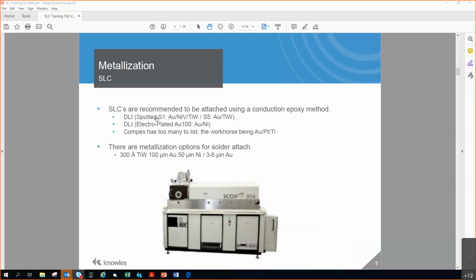What it didn't do is mesh well with our manufacturing process for DLI, because we do a lithography process, which doesn't go well with platinum. Compex uses what they call a scoring process, and basically it's a skim dice. They dice their borders around their parts, and that's fine. With a commercial application, you don't need the clean edges as much as you do in the defense market, where we would do litho and it would be a little bit cleaner. So that's why we go with the titanium tungsten gold instead of the Ti-Plat gold.